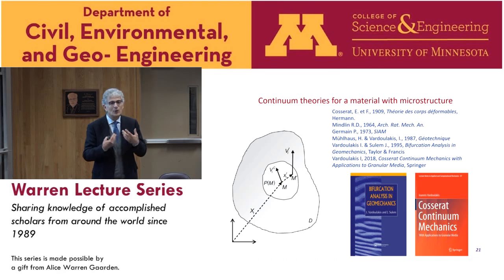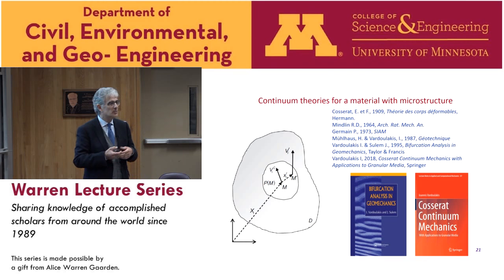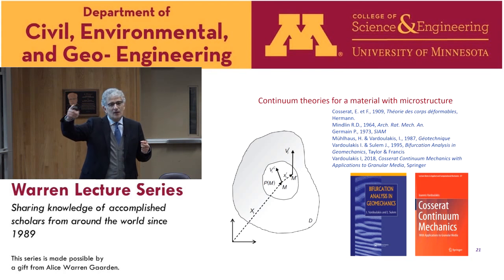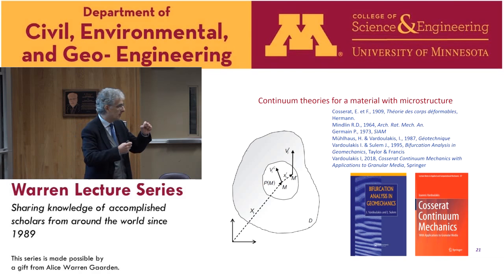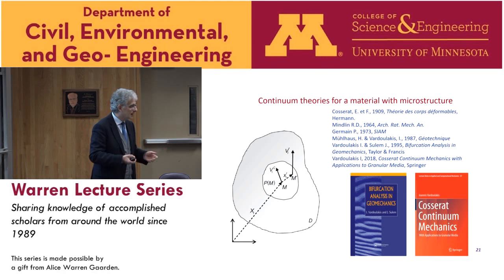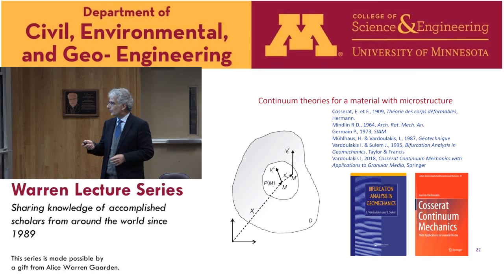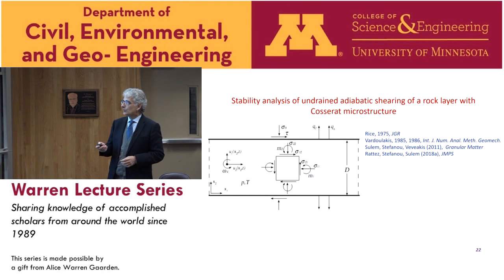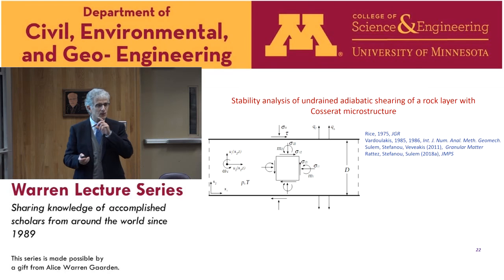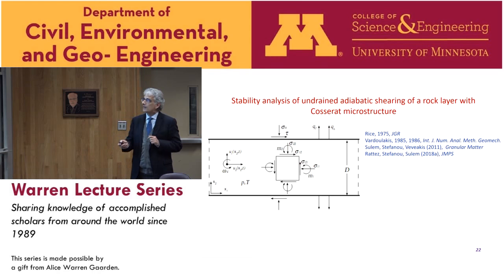However, in the very early applications of Cosserat theory, it was a bit disappointing because as soon as the wavelength of the deformation mode is rather large as compared to the grain size, we find that the Cosserat effects are negligible. So the applications fade away in some way until the 80s and the ideas of Yannis and Hans that it could be useful in strain localization analysis because indeed there is a strong interplay between the microstructure and the localization phenomena. So I would like to illustrate the effect of the Cosserat terms in one example, which is